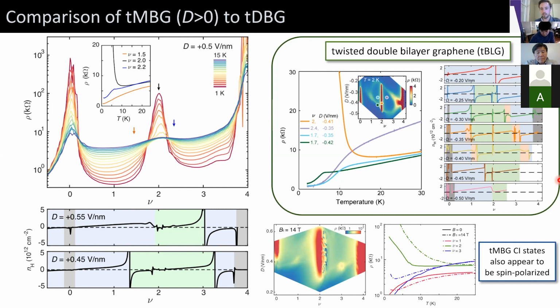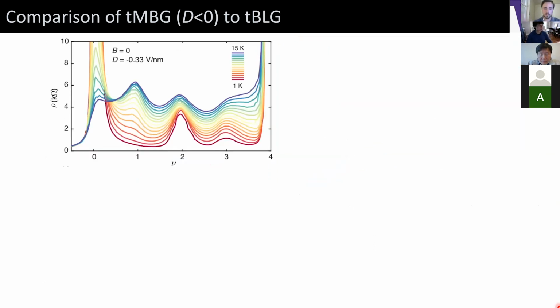And measurements in an in-plane field also suggest that these are spin-polarized states, the same as they were in twisted double bilayer graphene, where the device resistivity grows larger as we apply an in-plane magnetic field because the spin gap is getting bigger. Okay, so that one is somewhat trivial.